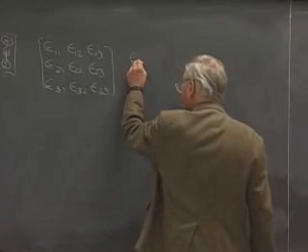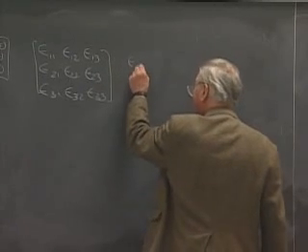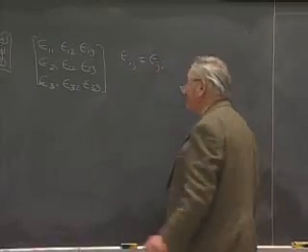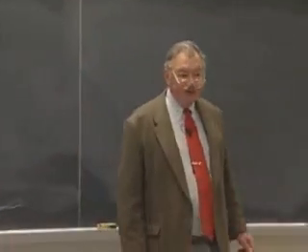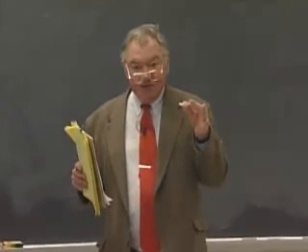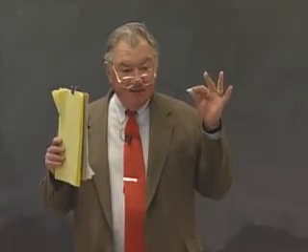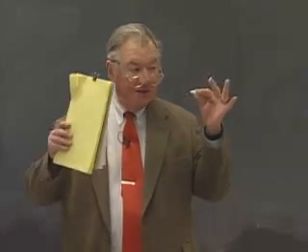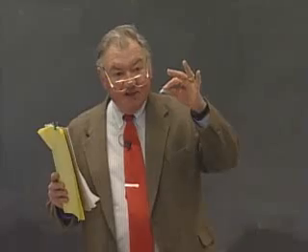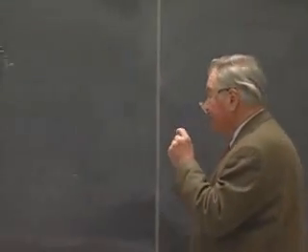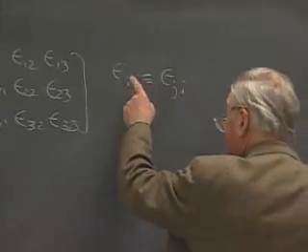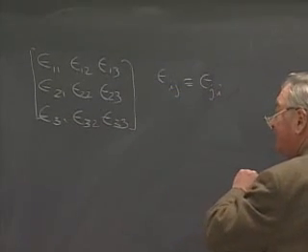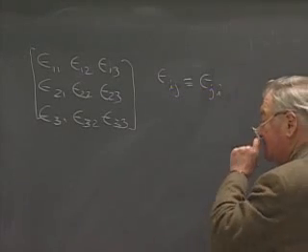We had to have epsilon ij identical to epsilon ji. The reason being that if these off-diagonal shear strains were not equal, the state that we would be defining was one of actual deformation combined with rigid body rotation. So unless this was the case, the definition performed by the tensor epsilon ij would define rigid body rotation as well.